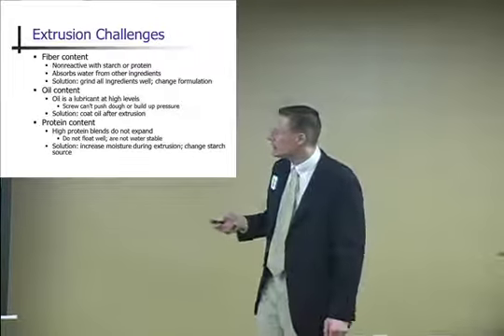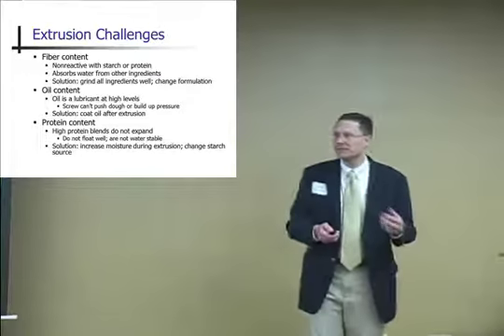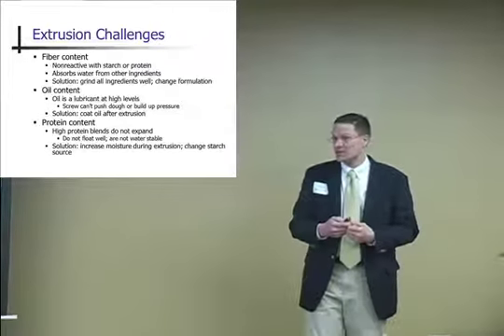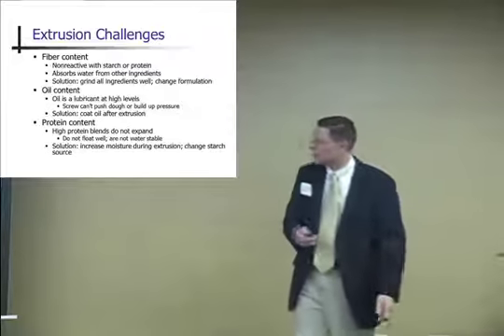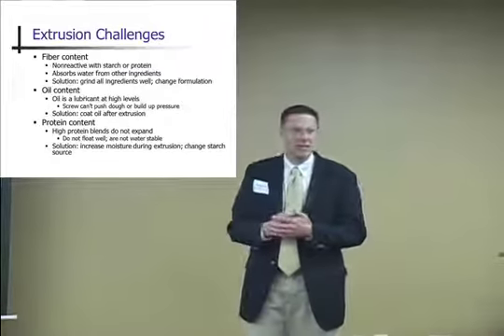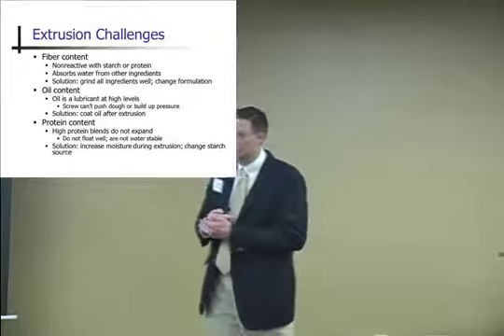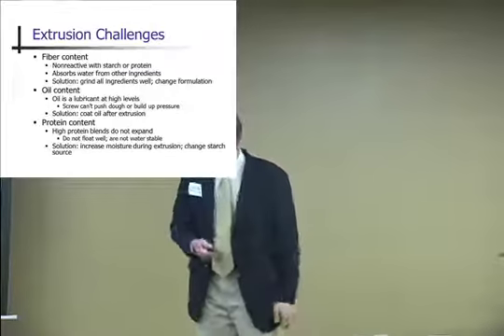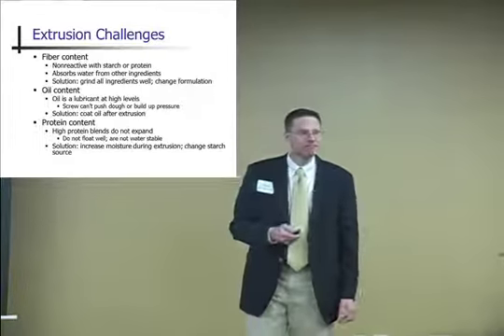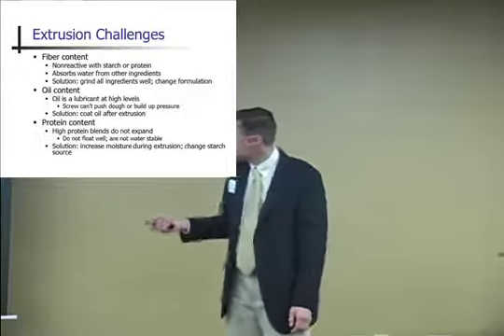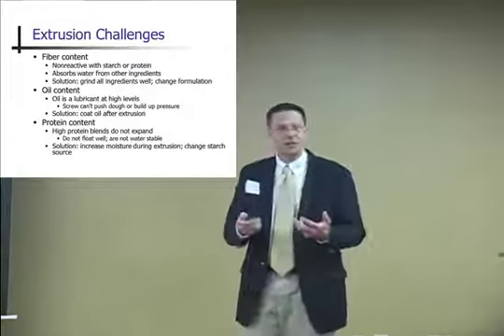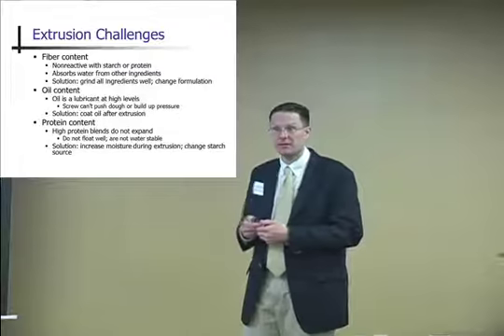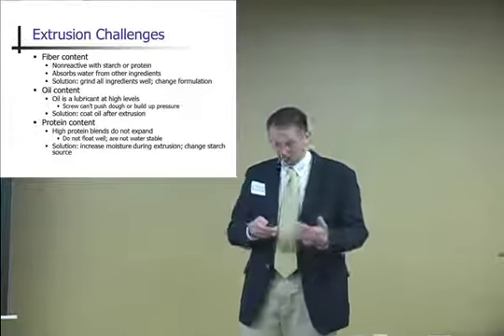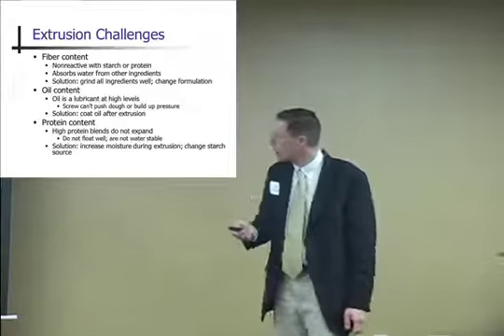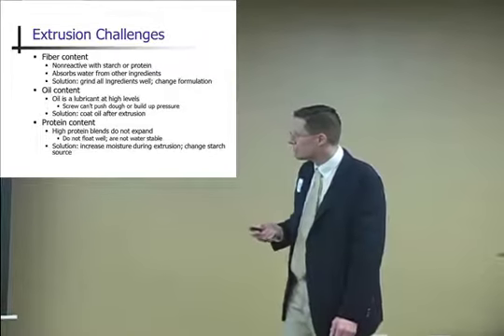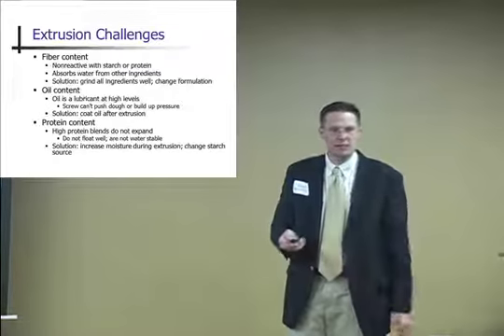Oil is a lubricant. Oil makes extrusion a challenge, especially for smaller diameter pellets. So if you need to add oil, my suggestion is do a post-extrusion coating, either a vacuum coating or other type of coating. That's my suggestion. Protein: high protein blends don't expand. That's why the starch is critical. So if you have a high protein blend, increase your moisture or change the type of starch that you have.